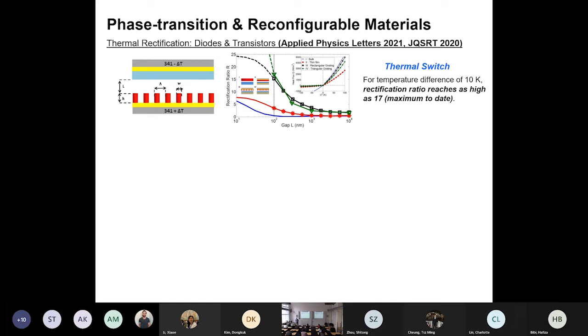And we calculated the heat transfer across the phase transition temperature, 341 Kelvin, by 1 Kelvin up or 1 Kelvin down. So plus or minus 1 Kelvin, plus minus 2 Kelvin, plus minus 5 Kelvin. And also we defined the radiative heat flux from bottom to up as the forward direction. And from up to down, downwards, as backwards. So we just need to calculate the ratio of these two heat fluxes, the forwards and the backwards.